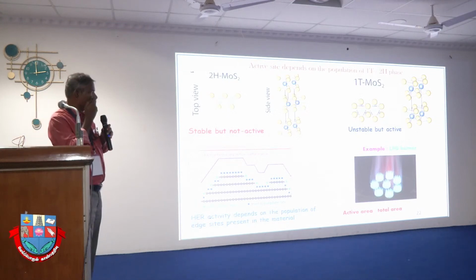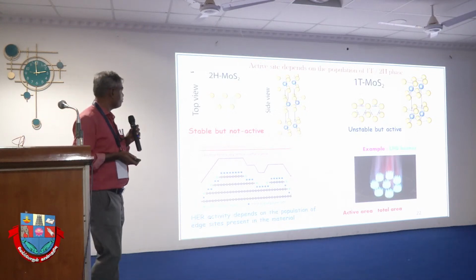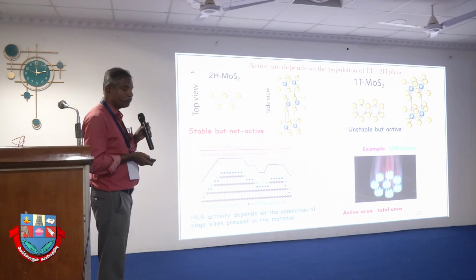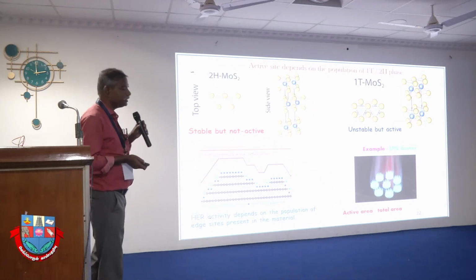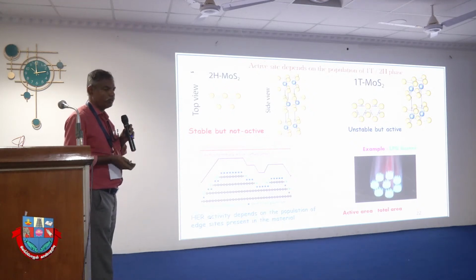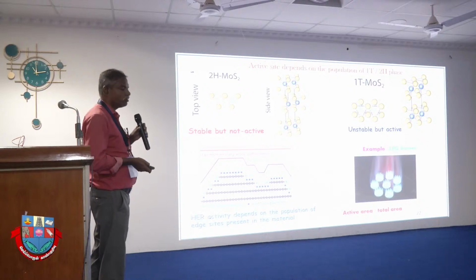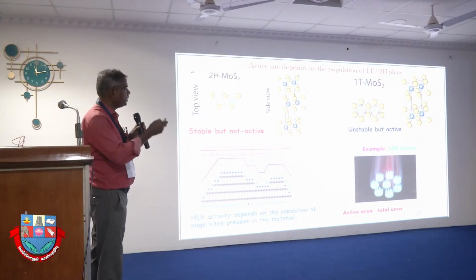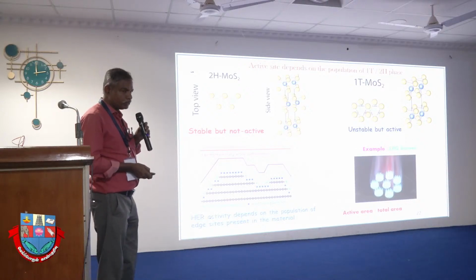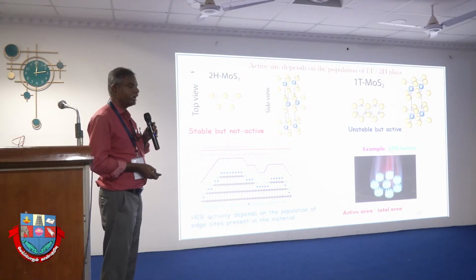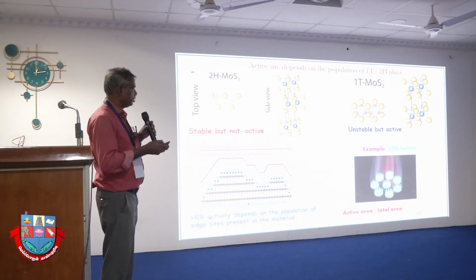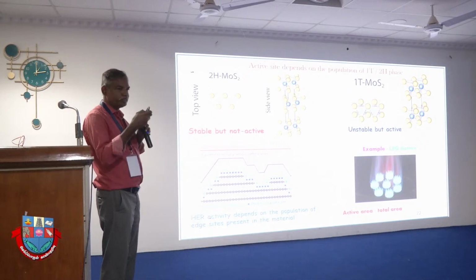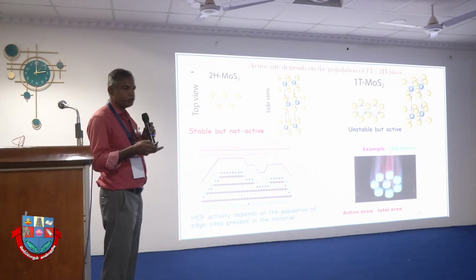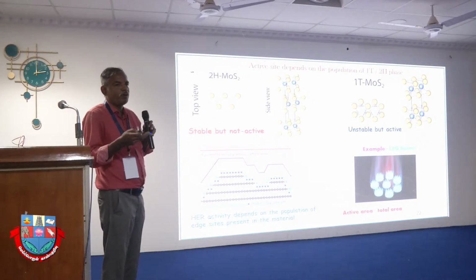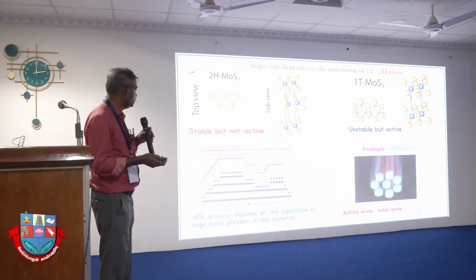I want to emphasize here that there are normally two forms of MoS2. The 2H is the stable form, which is available in the crust, but it's not active for HER. But the 1T is a metastable form. It has to be prepared in the laboratory, but it's highly unstable. So the stable form may not be that active, but the unstable form will be active, but we cannot hold the activity for a longer time. That's the problem with MoS2.